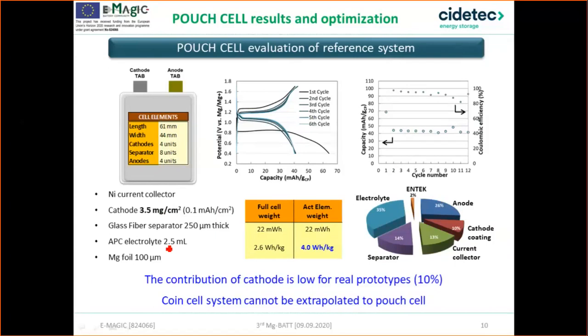This pouch cell delivered 40 milliampere hour per gram and was reversible for certain cycles. This pouch cell delivered 4 watt-hour per kilogram energy density, which is not a very competitive value. But the interesting thing when analyzing the component contribution to the pouch cell mass, we realized that the active material, the material giving the capacity, cathode coating, represented only 10% of the whole system. This is not realistic in a real device. And, well, we came up with the conclusion that coin cell system cannot be extrapolated to pouch cell level, and we need to optimize, to redesign the system at pouch cell.